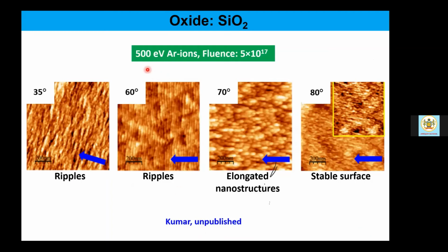I mean, this is 500 eV argon ions. Okay, and from a very low incidence angle of 35 degree to 80 degree, we get to see a stable surface at 80 degree, whereas elongated nanostructures were formed at 70 degree, and ripples were formed up to 69 degree, 68 degree or so.